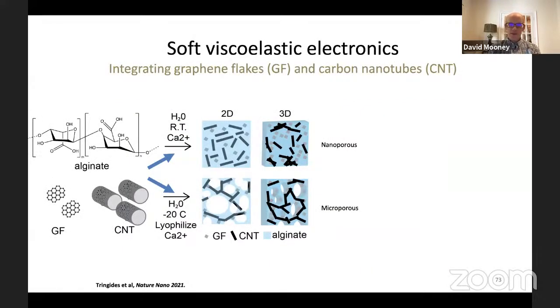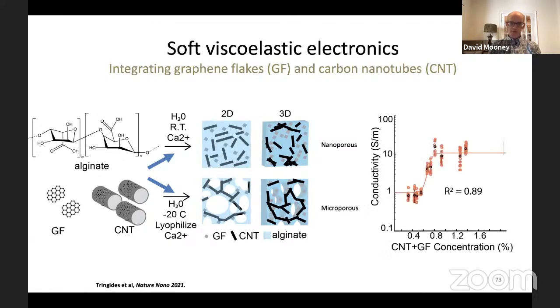As I mentioned, we want to make the electronics component soft as well and viscoelastic. So we're utilizing graphene flakes and carbon nanotubes to accomplish this, and to minimize the quantity of these materials, which could otherwise actually dramatically stiffen the gels. We use a technique to create microporous materials to concentrate the particles just in a fraction of the entire volume. And this allows us to get percolation, electrical passage, at very, very low solids content, where we don't have any significant impact on the bulk mechanical properties of the layers.